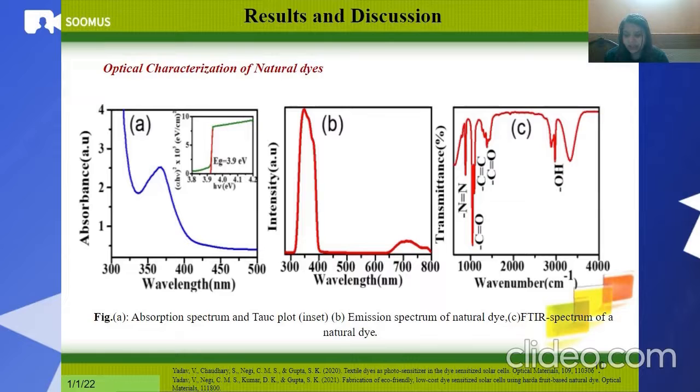The PL spectrum shows an intense and broad emission band from 300 to 420 nanometers, with a significantly weaker emission band within the 660 to 800 nanometer range. The first emission peak can be attributed to the band-to-band transition, whereas the second band observed at longer wavelength, which is in the visible and near infrared range, is linked to the delocalization of electrons in hydrocarbons that helps to harvest sunlight efficiently and improve the performance of the material.